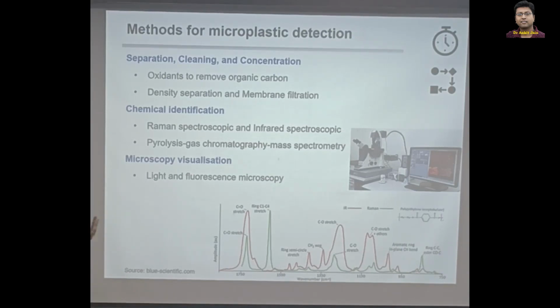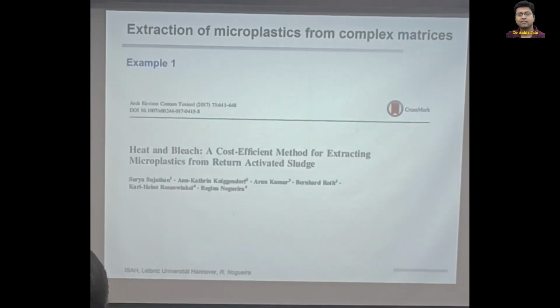Okay, this is a little bit the basics, and now in the three case studies, I will just mention the methods that were used. But never forget that the first step is the cleaning. If you need, but usually our samples are not very clean, it means we have to clean them in order to detect the microplastics. Okay, and then since we wanted to detect the microplastics in this sludge, we had to develop a method, and we call the method heat and bleach. Why? We use bleaching agents to degrade the organic matter, and since this degradation happens faster at higher temperature, we call our method heat and bleach.